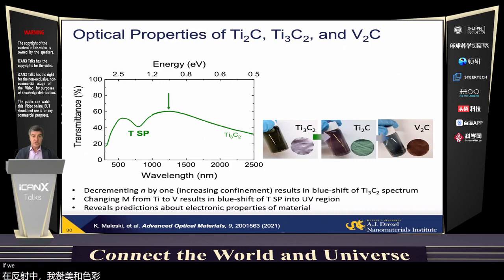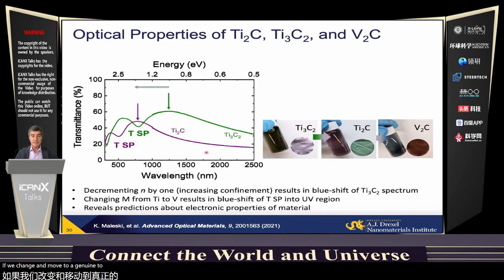And let me give you just one example. I don't have much time to go into details here. Let's take 3 different examples from this family of materials. Titanium 3C2 will have transverse surface plasmon at about 780 nanometers. As a result, it will be green in solution, but it will be a purple-like color in reflection, a complementing color. If we change and move to titanium 2C, we will shift the plasmon resonance lower, and we will get it at about 550 nanometers. As a result, it will become green in reflection, but purple, reddish in transmission.